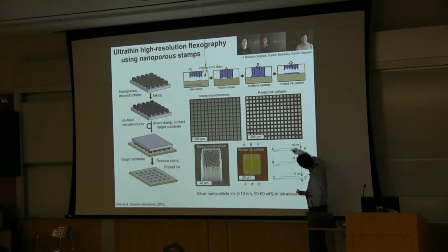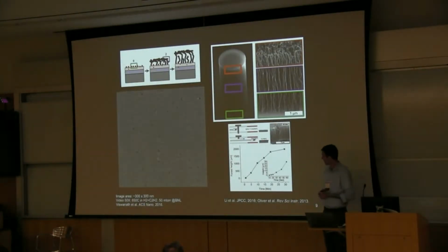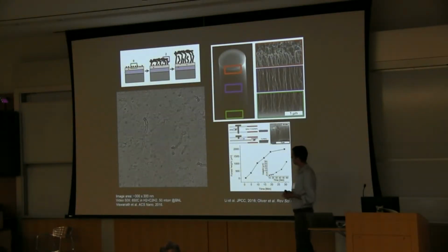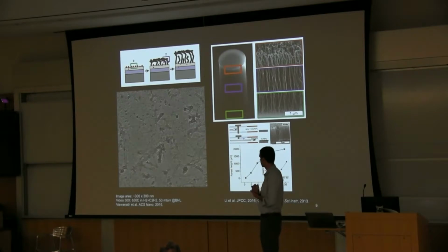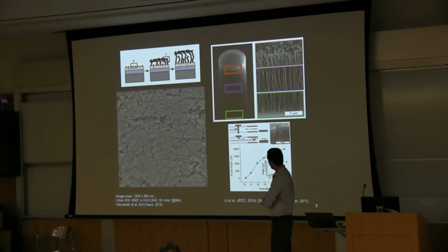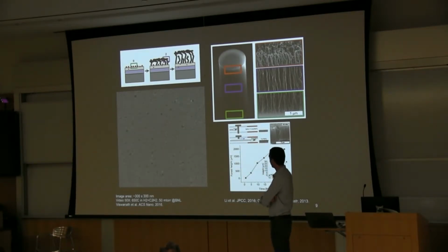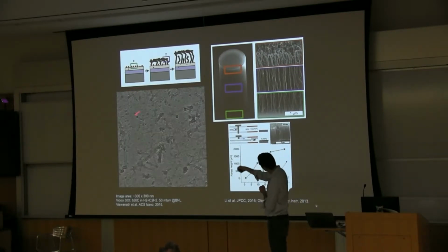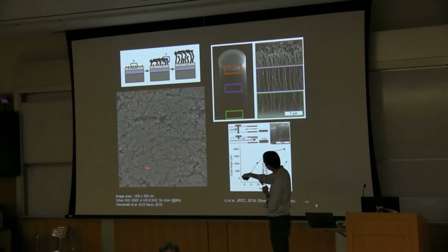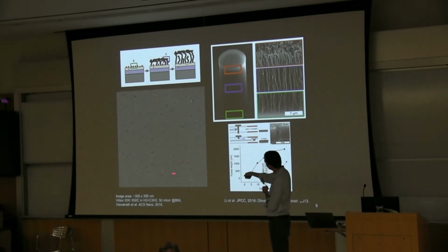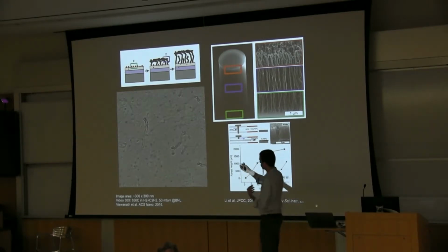This one ends up at about 40 to 50 nanometers across its breadth. So we make these stamps from carbon nanotubes, and it's something we've worked on in my group since it started almost 10 years ago, and we've understood a good amount about how to make these vertically aligned nanotube forests. This is just to give you the visual picture of the growth, an environmental TEM video accelerated by 50x, where the nanotubes are growing toward us.